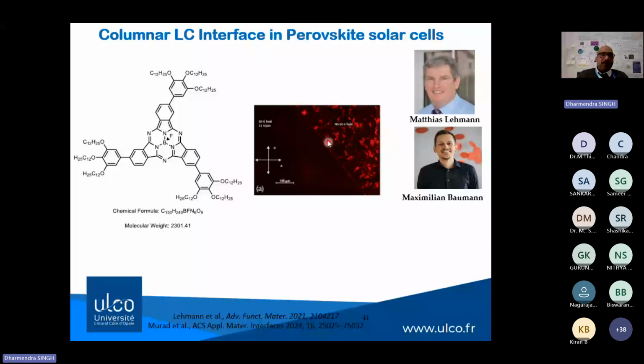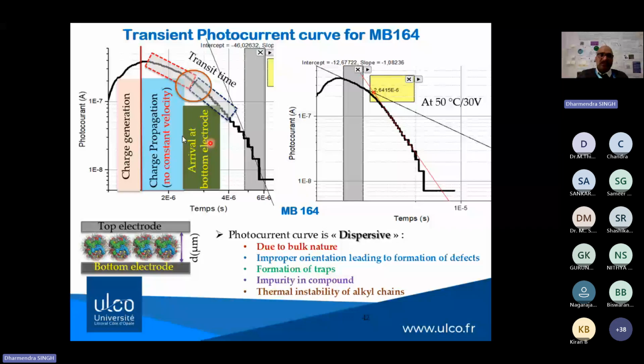So what happened when you applied the field? We investigated the charge carrier mobility and the charge transport phenomena. Because this molecule was very heavy, we got a dispersive photocurrent curve. Here you can see the different regions. In the first region, when you irradiate the material with laser light, charge generation takes place, and after that the charges propagate from the top electrode to the bottom electrode.